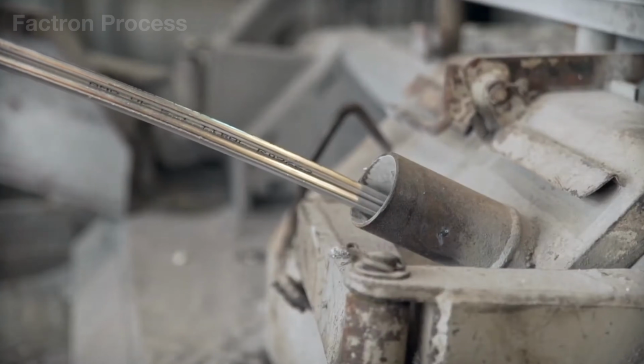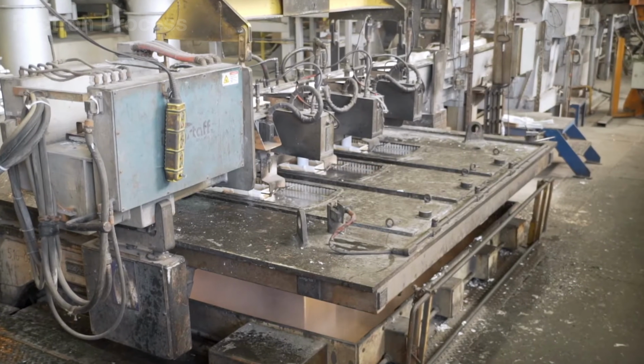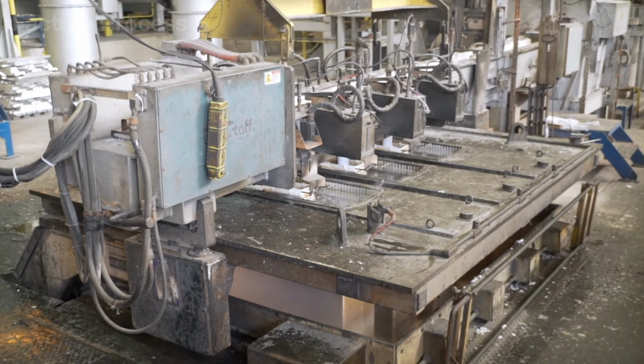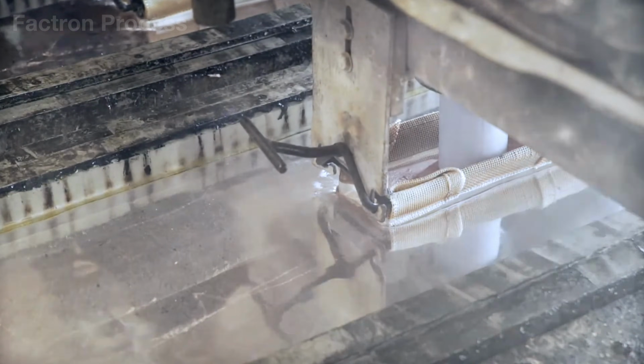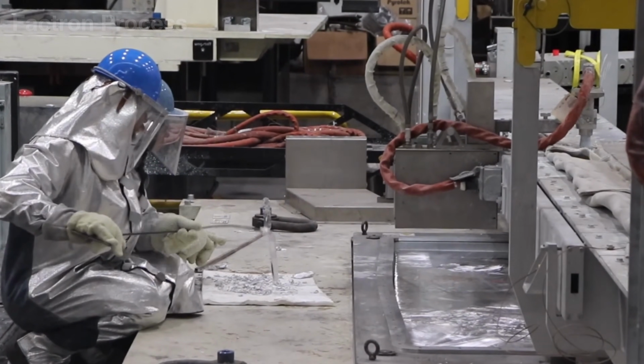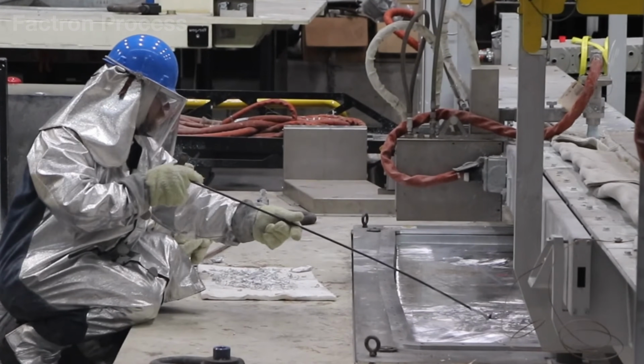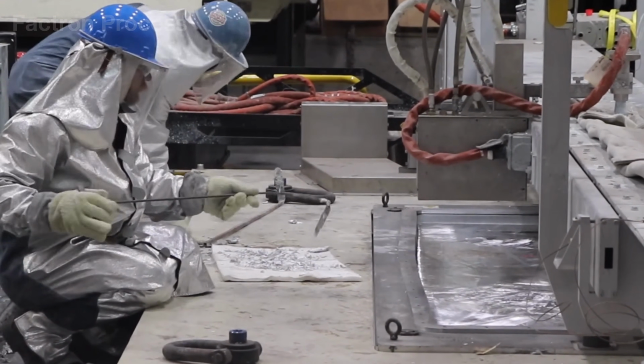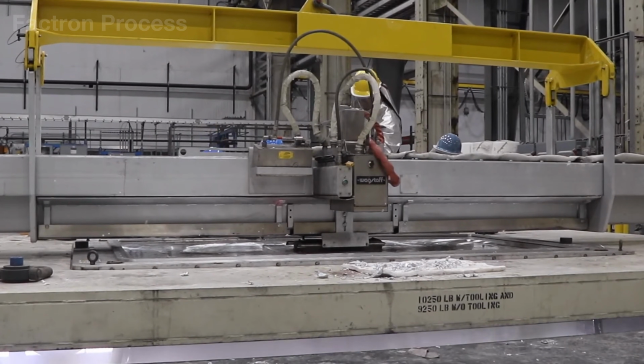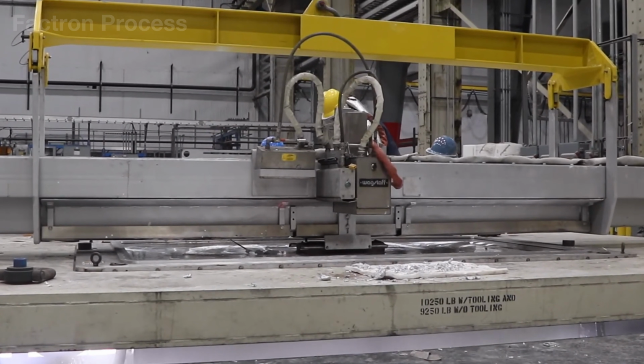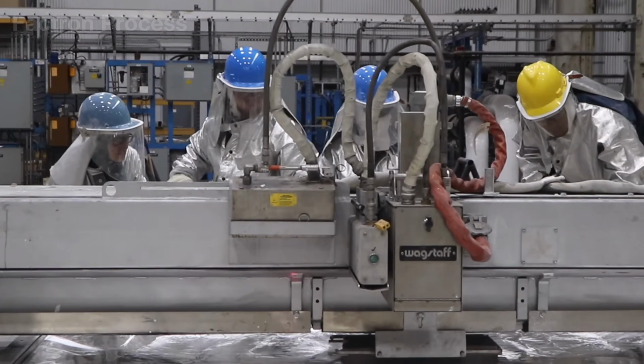The roller table then reverses direction, sending the aluminum sheet back through the rolling stand. The gap between the rolls is reduced again, and this back and forth compression is repeated several times. The slab becomes thinner and longer until its original shape is almost unrecognizable. By the end of the process, a slab initially measuring tens of inches thick has been transformed into an aluminum strip only about 0.07 to 0.28 inches thick.